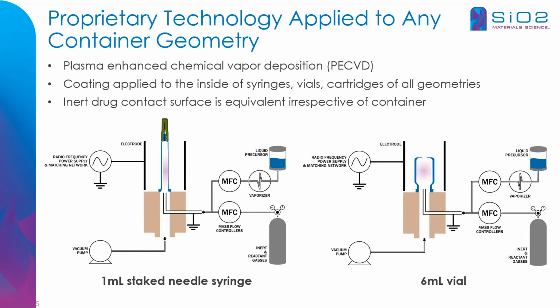And what you can see here is a coating system for vials as well as pre-filled syringes. Coating them one by one gives us very good uniformity of both the thickness and the chemistry. And this coating system that I just presented to you has been scaled to an industrial level where we're able to manufacture upwards of 10 million vials per month.